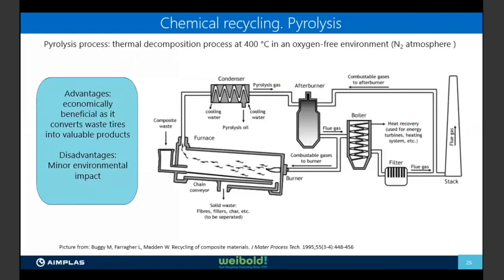The pyrolysis process is a thermal decomposition process at 400 degrees in an oxygen-free environment, and it is economically beneficial as it converts waste tires into valuable products. The main problem is the environmental impact, but compared to combustion and gasification, the impact on the environment is less. Here you can see a picture of a recycling process for composites, but with tires it is more or less the same.